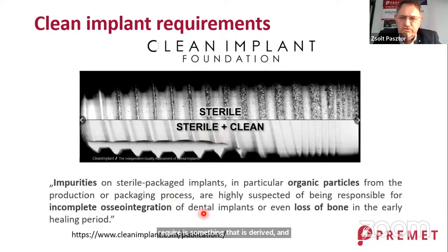And the finding that they made is that impurities on sterile packed implants, in particular organic particles from the production or packaging processes, are highly suspected of being responsible for incomplete osseointegration of dental implants, or even loss of bone in the early healing period.